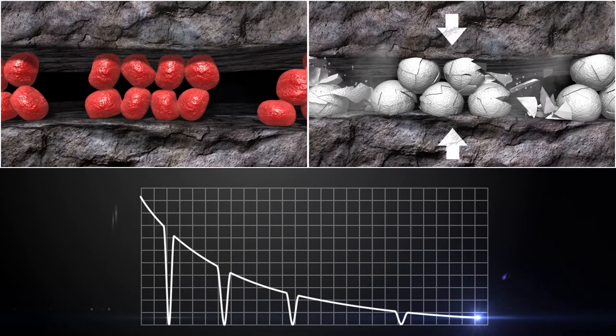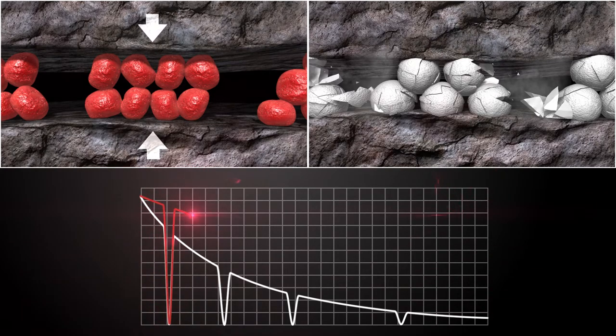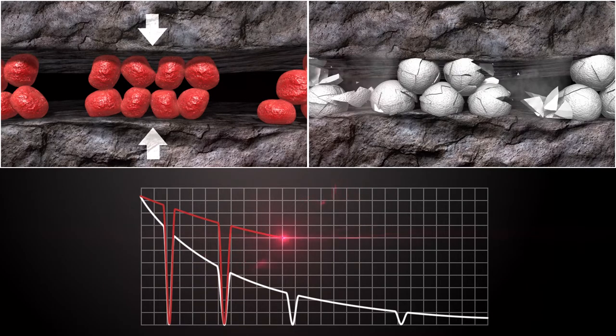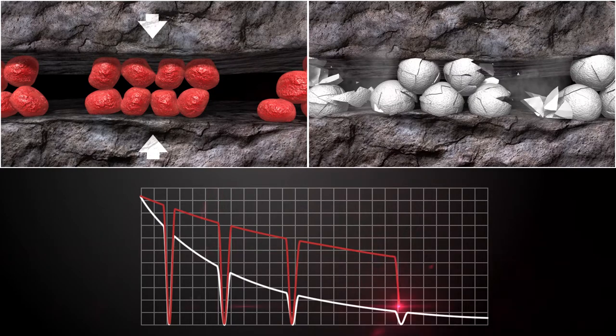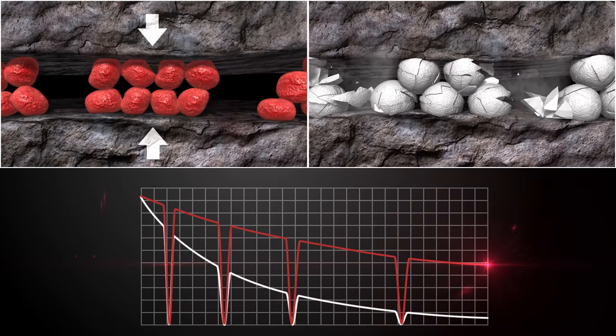These stress changes often cause uncoated proppants, especially brittle ceramics, to fail prematurely under wet, hot, downhole conditions. Curable resin-coated proppants such as BlackPro resist these cyclic stress changes by forming a flexible lattice network that redistributes the stresses through the proppant pack, reducing individual point loads on each proppant grain. This feature leads to improved proppant pack integrity and well production.